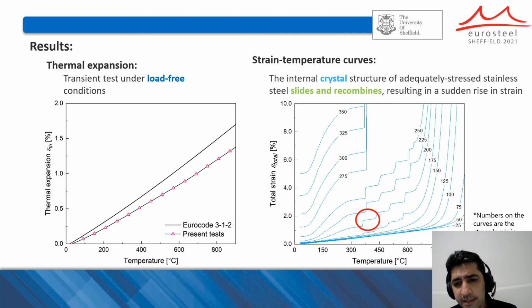The reason for these sudden jumps is that sudden changes occur in the microstructure. Actually, the internal crystal structure of austenitic stainless steel slides and recombines when a significant amount of load and temperature is applied to the material, and as a result, we can see these jumps.